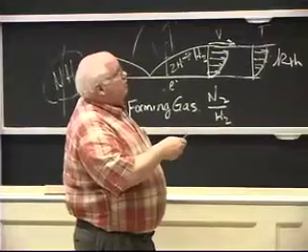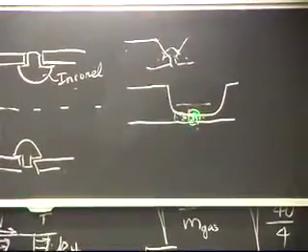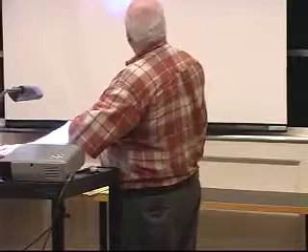Now, you can see if you get most of the heat to the workpiece, and in gas tungsten arc welding, let's say we're trying to make one of these pipe welds, we want to put the heat not into the electrode, but into the base plate, because that's what I'm trying to melt. So I tend to use straight polarity. There are some other reasons I use straight polarity, which we'll get into later. If I'm doing gas metal arc welding, where I have a steel electrode that's going to have drops melting off, I actually change to electrode positive, which we call reverse polarity rather than straight polarity.